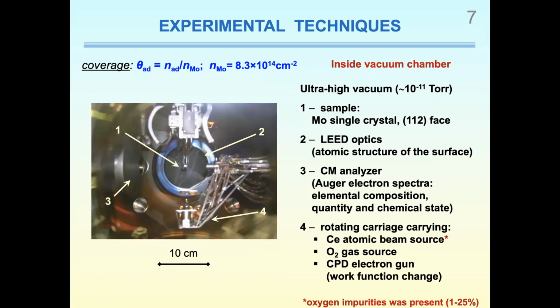All our experiments were performed in an ultra-high vacuum chamber. We utilized three methods for the surface state characterization: low energy electron diffraction to define the surface structure, electron spectroscopy for elemental composition analysis, and contact potential difference for measuring the work function changes.